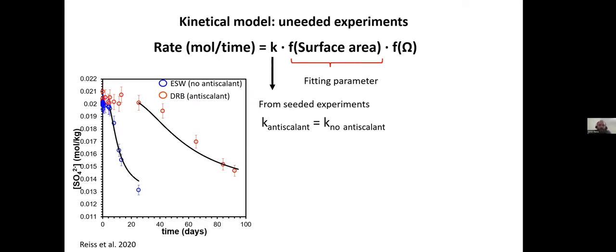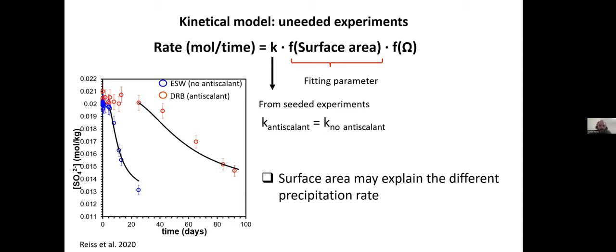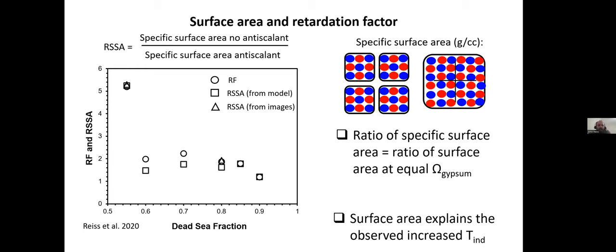So just to verify the results of the model, we could compare the specific surface area without scale inhibitor to the one with scale inhibitor. These are basically the same experiments. So at each oversaturation I look at, I have the same amount of precipitate mass. So the specific surface area would give me the ratios of surface areas. And I also computed them from the model, the RSSA from the models is the squares. I also measured them from images where it was possible, when I had enough crystal surfaces, the triangles, and we see that the specific surface area really sits well with the retardation factor.